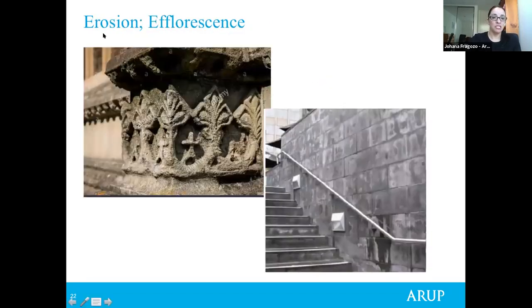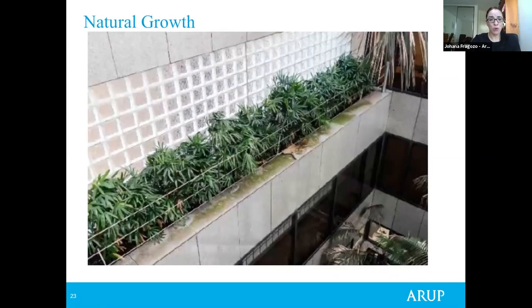There could be erosion as well. This is particularly common in architectural features, decorative features such as carvings, and it is caused by the long-term action of wind and rain. And efflorescence could be due to leachate deposits that occur where the lime or the grout has been dissolved. Due to moisture transmission, it reacts with atmospheric carbon dioxide and forms calcium carbonate or leachate deposits. These two defects are mainly of an aesthetic nature. Organic growth occurs when there hasn't been good design detailing, such as in flat edges, and therefore water accumulates and organic growth occurs.